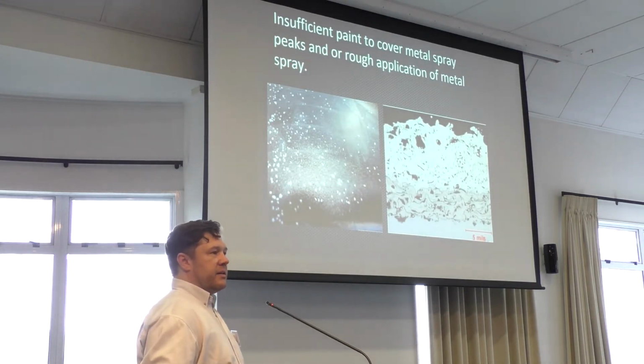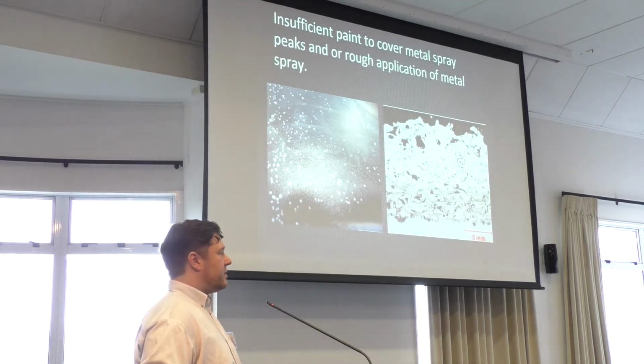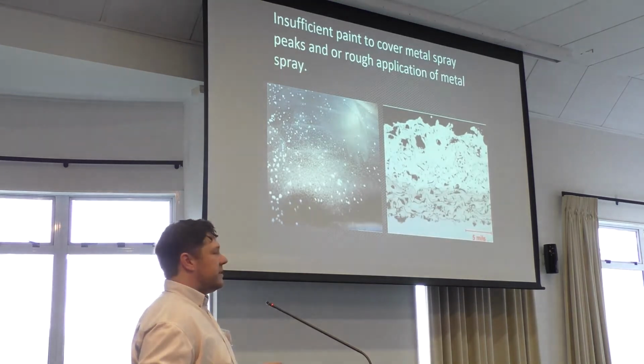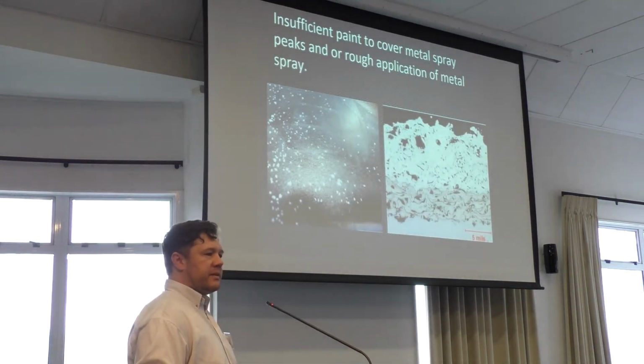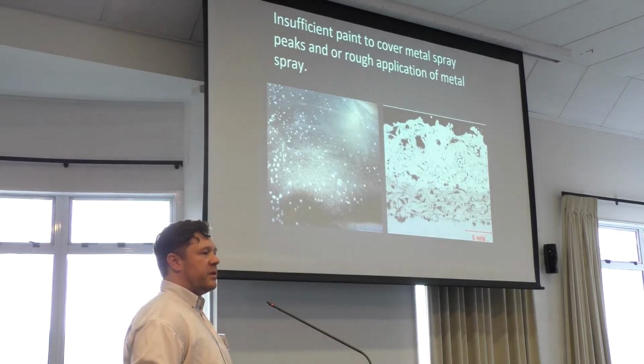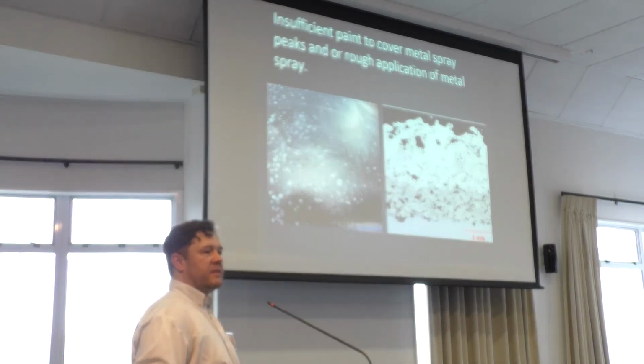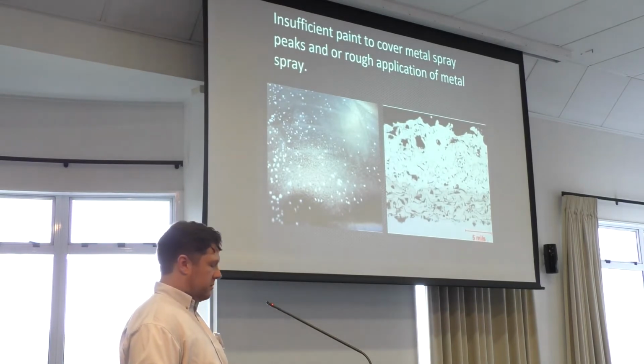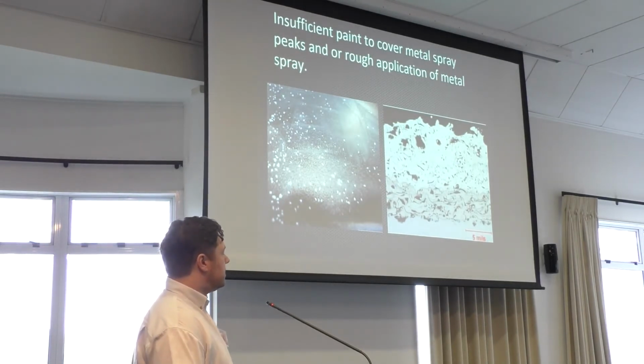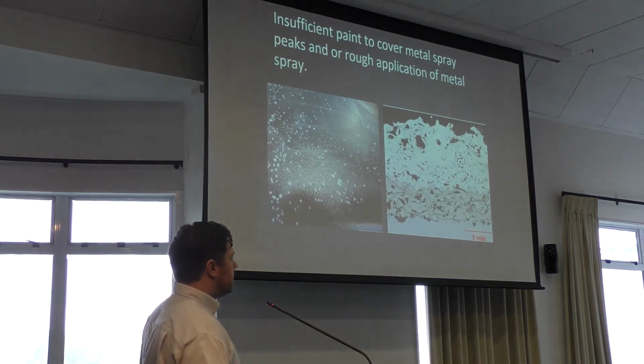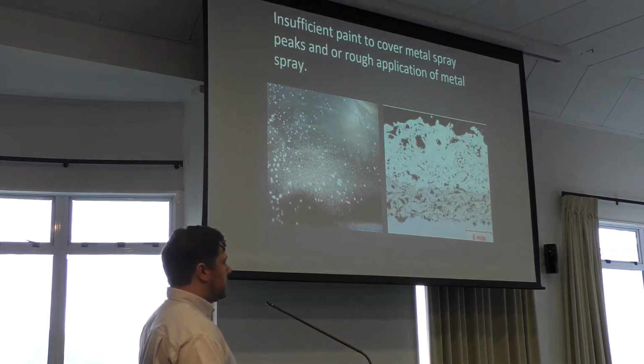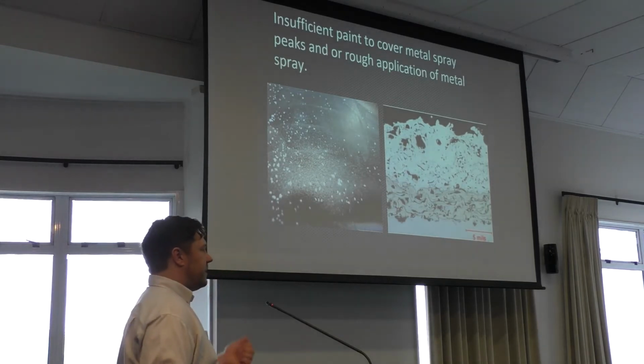The denibbing and rogue peaks have been used in some of the standards, so it gets used by everybody, but it's not clear enough for me. I think that sanding it is a better way to put it, so that we've got a clearly defined value that we can meet before we apply a paint on top. And the surface roughness is very much dependent on the machine you use, how you set it up, and there's a lot of other variables. You can get surfaces without rogue peaks if you know what you're doing. That's correct. So it is down to machine maintenance, machine settings.